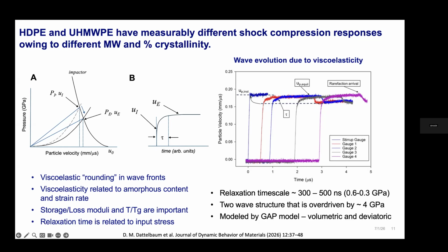This rounding and evolution of the structure has been proposed to be related to viscoelasticity. You can think of this kind of like silly putty. If you smack it really hard, it's going to respond with a stiff response, but over time, it relaxes. And that's what's actually happening under shock loading. You shock it, and then the material relaxes. As it relaxes, you can see the evolution in the wave profile, and the rounding is the signature of that relaxation.